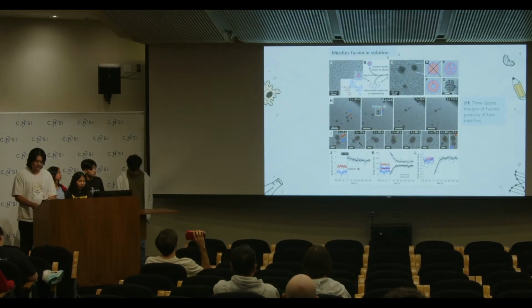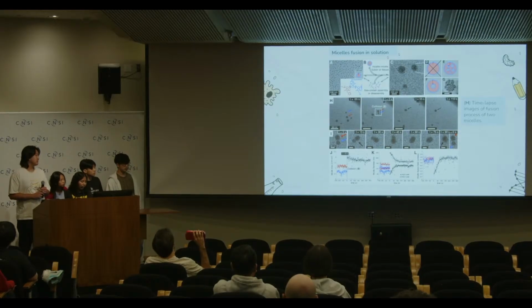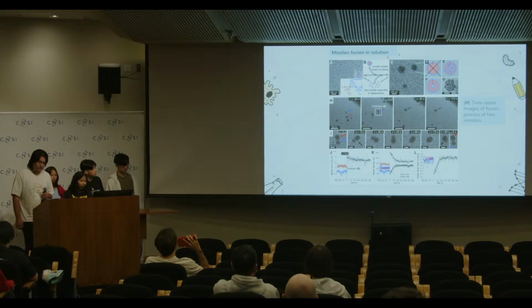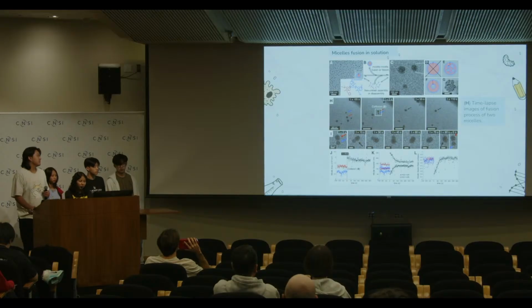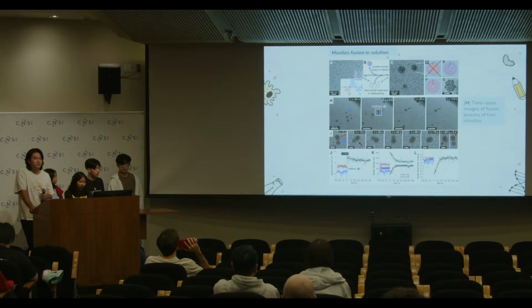Here we are able to see half of image 6. We are able to see in part H micelles fusion in solution. This is a time lapse of the fusion process of two micelles, something that we wouldn't be able to see in regular TEM as the samples will be frozen. Similar to image H, image I also shows a different time lapse in fusion.